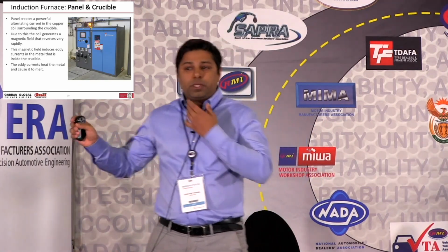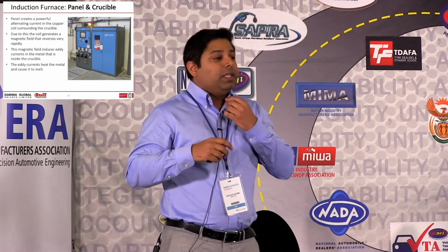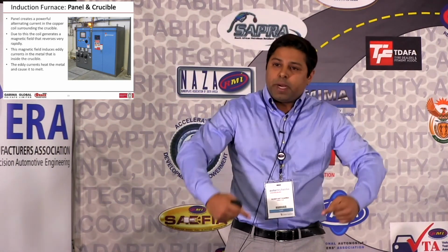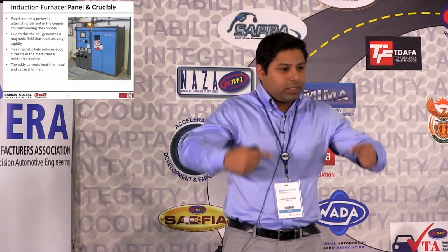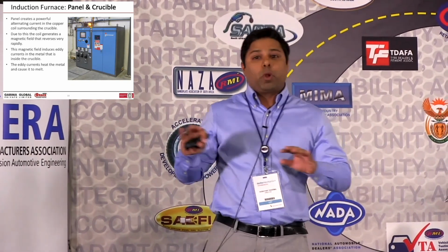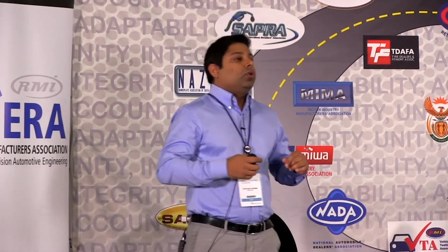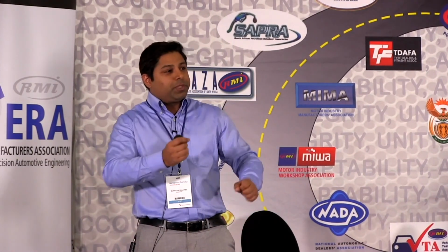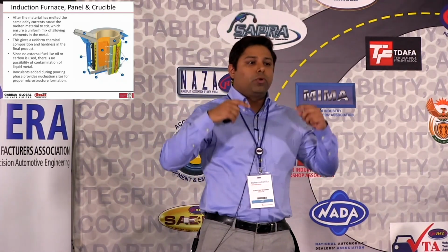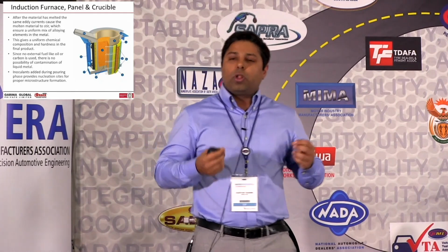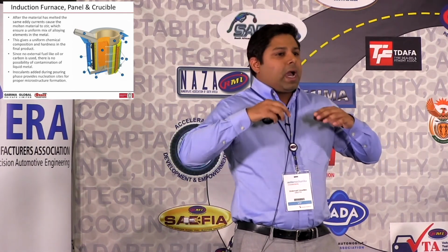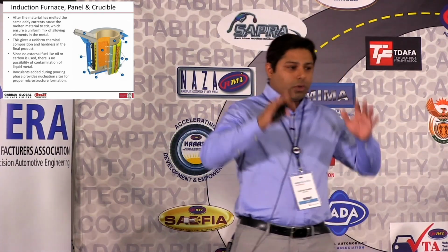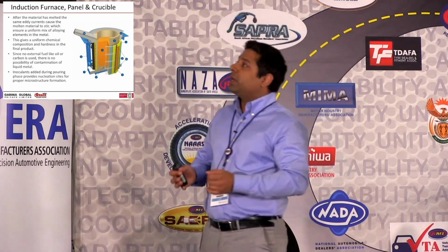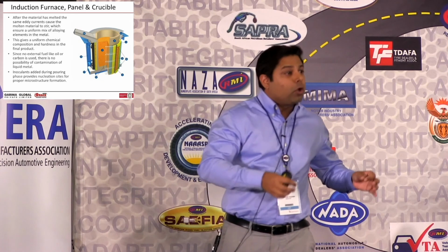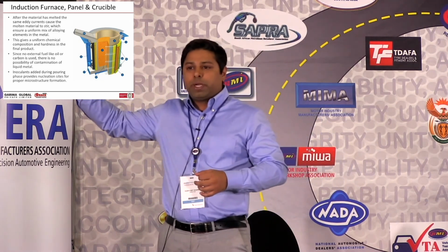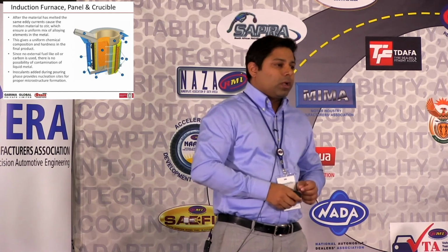Now this also helps, once the metal has been melted, these eddy currents keep the metal in a flux. They don't let the metal sit, which was a problem in the older technologies. So obviously you cannot take a spoon and keep stirring this metal, but these eddy currents don't let the metal sit. So all the ferroalloys that you put in there are uniformly distributed throughout the whole crucible. And that's how you get a nice uniform chemical composition when you pour this metal into the centrifugal molds.